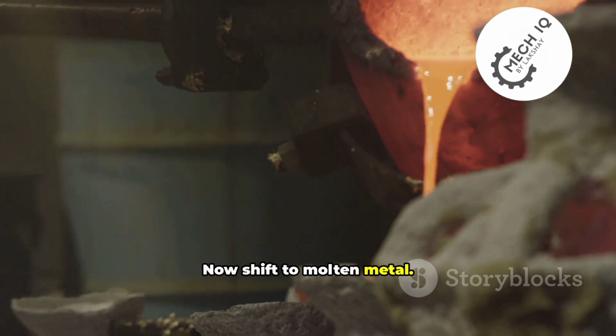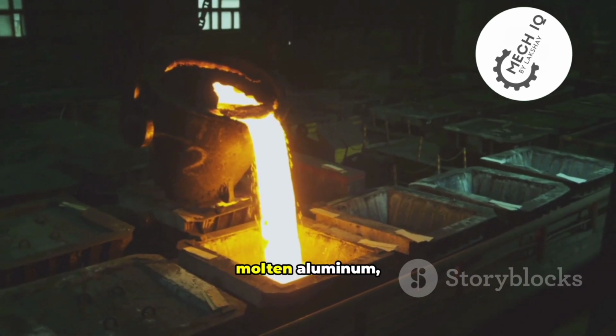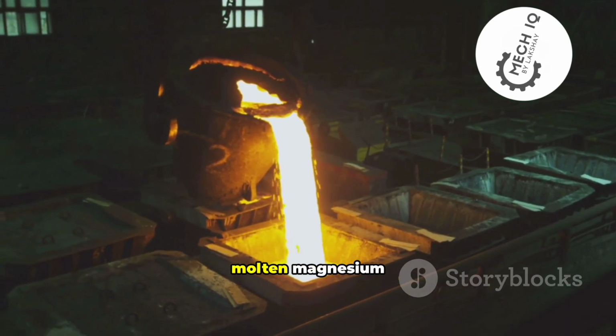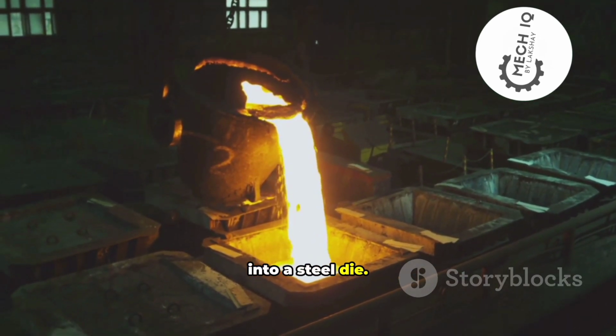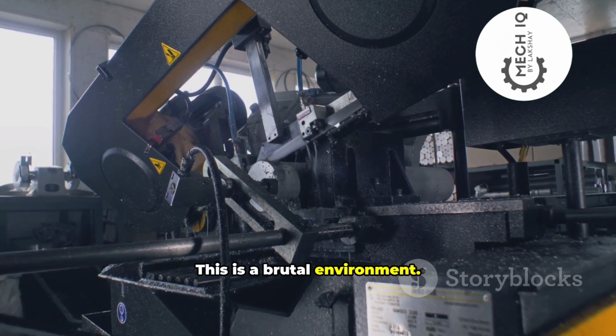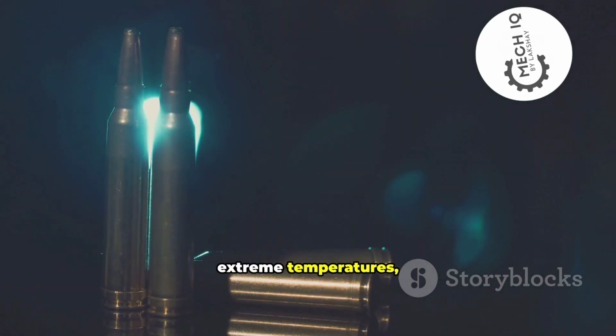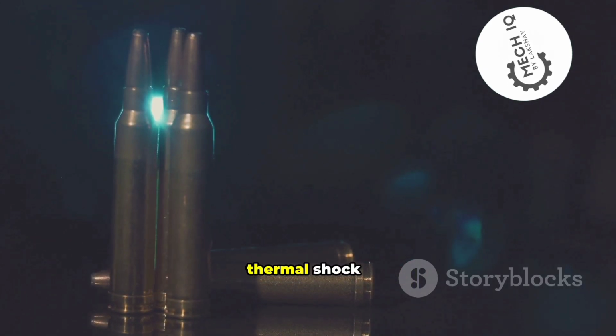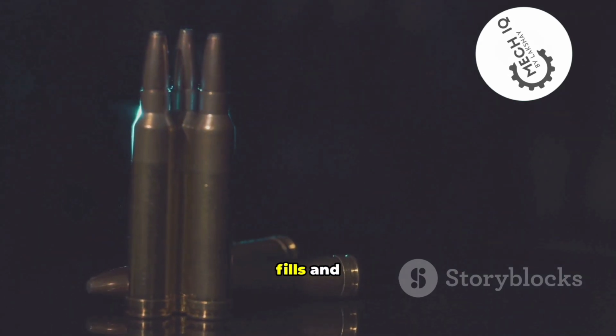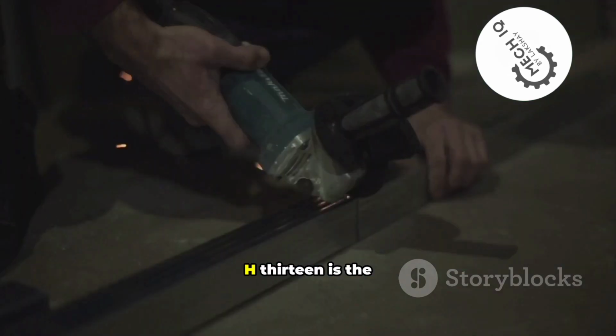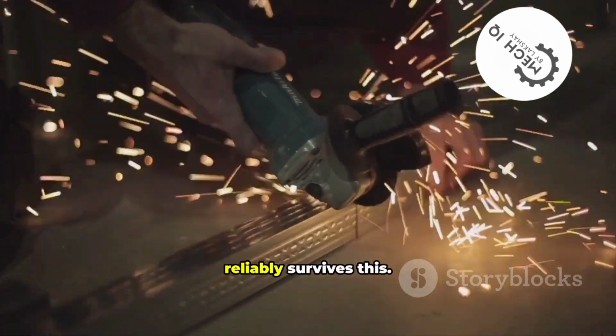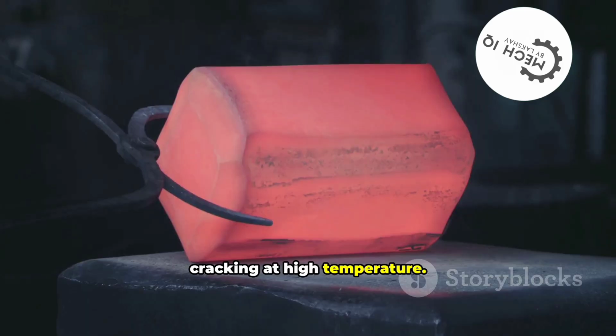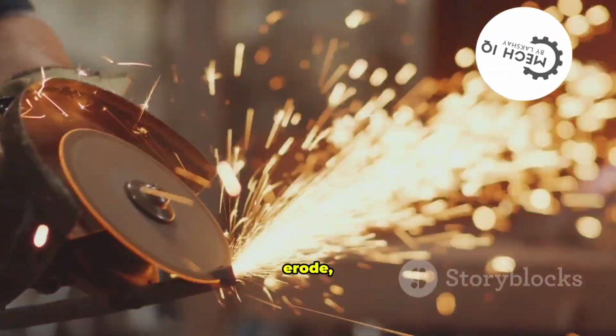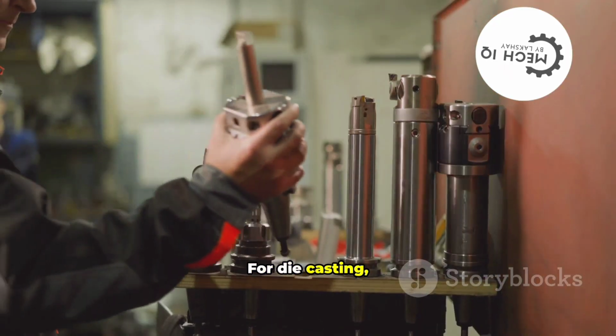Now shift to molten metal. Die casting forces molten aluminum, molten zinc, molten magnesium into a steel die. This is a brutal environment. The die faces extreme temperatures, high pressures, and constant thermal shock, cycling between hot fills and cooling lubricant sprays. H13 is the only steel that reliably survives this. It maintains strength and resists cracking at high temperature. Other steels would soften, erode, or crack quickly. For die casting, H13 is the industry standard.